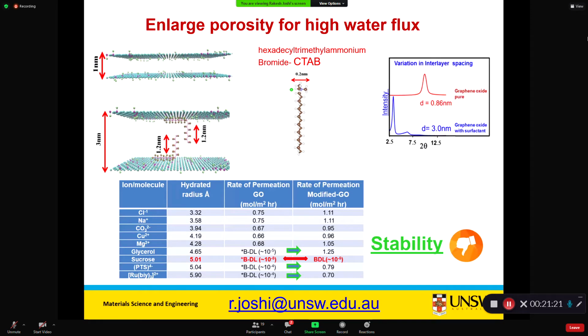Then for graphene oxide, if we don't change the morphology, we cannot do any membrane applications. So we thought of playing with the porosity of the graphene oxide membrane. At that time I knew that making it smaller would be difficult, so let's make it larger. So what we did, I used the surfactant CTAB. Someone suggested I use a surfactant, as it can attach to graphene oxide nicely.